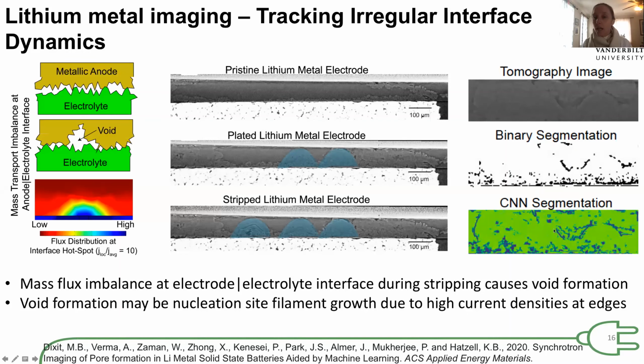This is the sample that we used with that first quantification. And why are we interested in this? Well, if we can track where the pores form, which basically are going to be sites where ions are stripped out of the lithium metal, we can potentially look at the ionic flux at this interface and capture dynamics of ion transport. In particular, we're interested in understanding how homogeneous this stripping and plating behavior is.